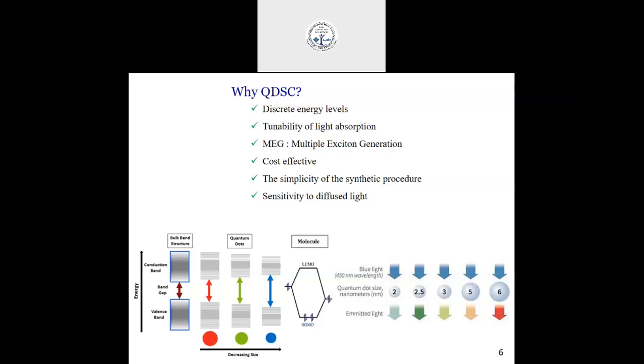Because of the discrete energy levels, when you shine a light of a particular wavelength, say in the second figure, if you see 450 nanometer, depending on the size of the quantum dot, the emitted light has its particular color. So it is all dependent on the band gap. If you have a 6 nanometer sized quantum dot, and if you shine blue light, the emitted light is in the red region. Whereas if you have a smaller quantum dot, that is 2 to 3 nanometer, you have it in the blue to green region. Basically, light absorption can be tuned depending on the size of the quantum dots.